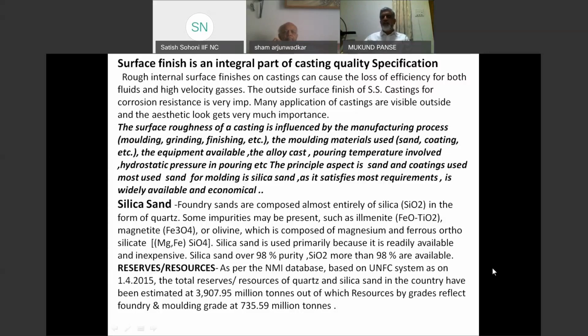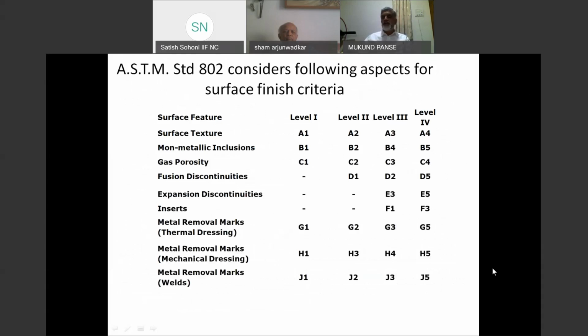In India, you get very easily more than 98% pure SiO2. It has small quantities of ilmenite, that is FeTiO3, and magnetite, but 98% purity is good enough. And the Allahabad sand, which is on the banks of the Ganges, is supposed to be one of the best sands in the world. As per the NMI survey in 2015, the total silica sand reserves in the country are 4,000 million tons, out of which around 735 million tons is suitable for foundry use. That is, sufficient stock of silica sand is available.